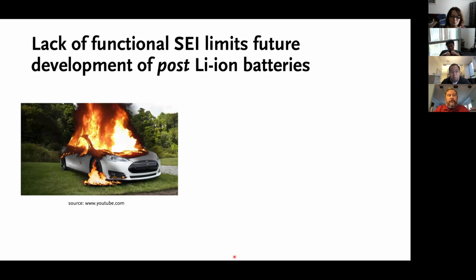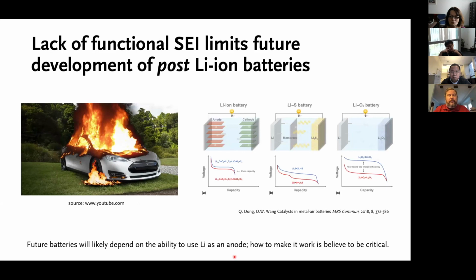And you may be noticing, from my previous slide animation, that I showed the anode, the cathode, different from the typical cathode. And this is because of the enormous success we now have with the cathode material as typical intercalation layer structures where lithium can go in and come out at ease. And they are great because they allow for repeated charge and discharge, but they're also horrible because they typically feature transition metal oxide that carry a lot of "dead weight."